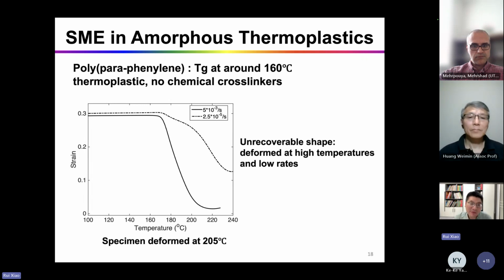You can see that these polymers have a TG around 160 degrees C. Even if we program it at 205 degrees C, very high above TG, you can see if we program the SMP very fast - deform it very fast and cool down very quickly - you can still have very good, decent shape recovery performance.